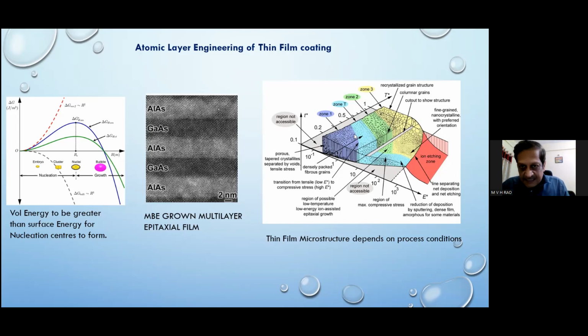Here is one very popular colored picture I'm showing, which tells the microstructural nature of the thin film based on vacuum conditions, deposition rate and substrate temperature. These are the things that control the microstructural evolution of the thin film. If we deposit very fast at low temperatures, we'll end up with a very columnar, very loose type of grain growth, which will not be stable. It will not adhere properly. Ultimately, whenever we are depositing a film, we need a very strongly adhering one.